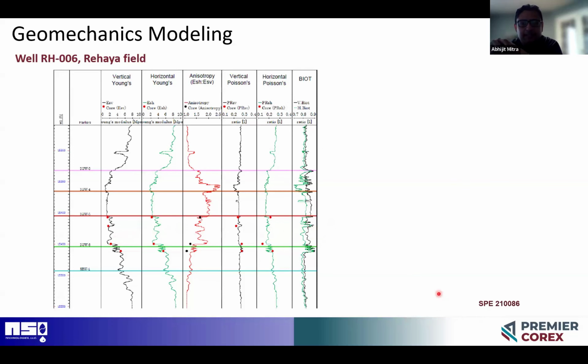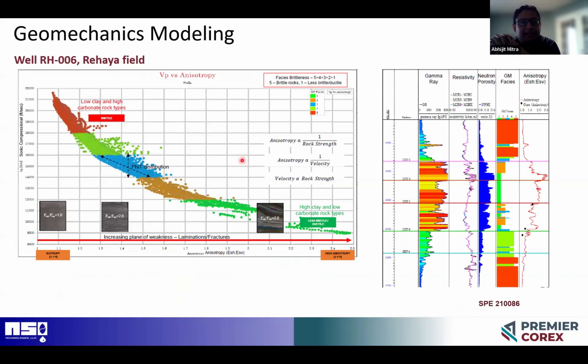For example, in the next slide, what we have done here is plot the P-wave velocity as a function of the elastic anisotropy, expressed as the ratio between the Young's modulus perpendicular and parallel to bedding. What we see here is that if the sonic velocity is extremely high, the anisotropy is extremely low, and vice versa. And not only that, the very high sonic velocity is accompanied by low clay and high carbonate content, whereas where we have very high anisotropy, we have extremely high clay content but very low carbonate content. So this is one of the things that we can do. Next slide, please.